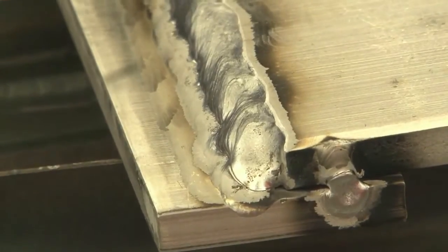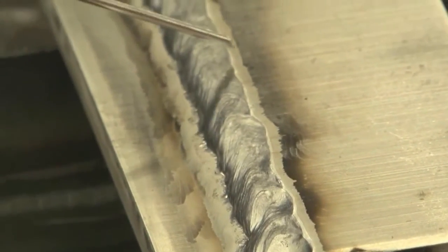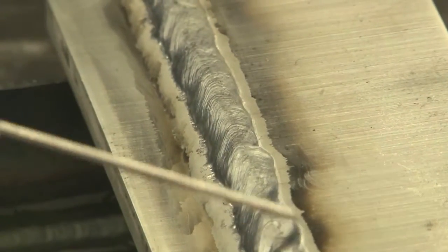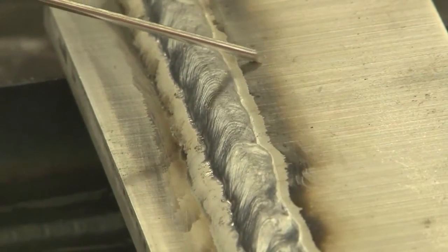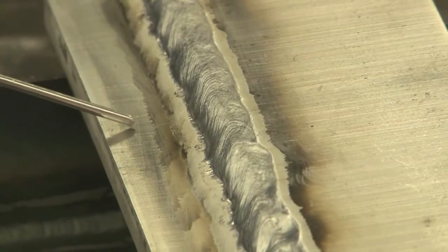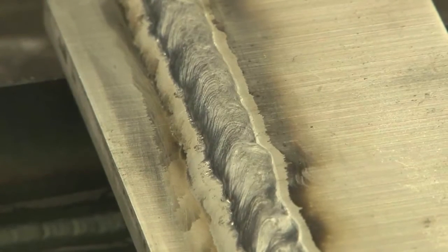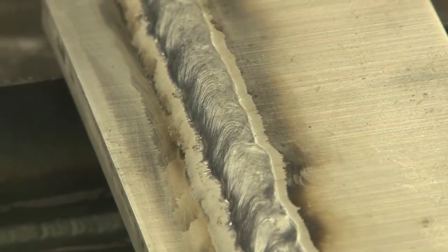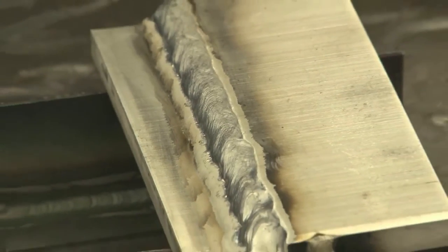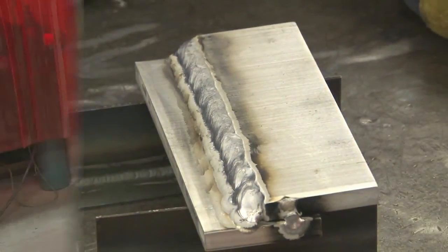So now I've added my third pass and I've tied my second pass into my top plate. I don't have a lot of buildup at this top plate. It's a nice smooth transition from here down through the fillet weld and onto the base plate. So I've used a 3-pass welding technique to make a 3/8 inch fillet weld in 3/8 inch material.